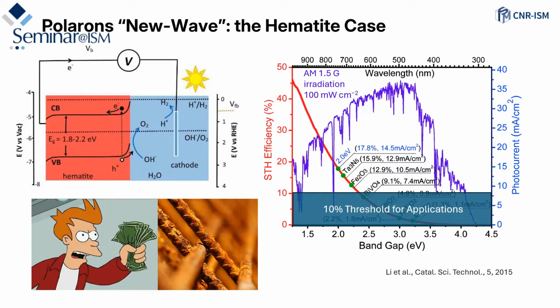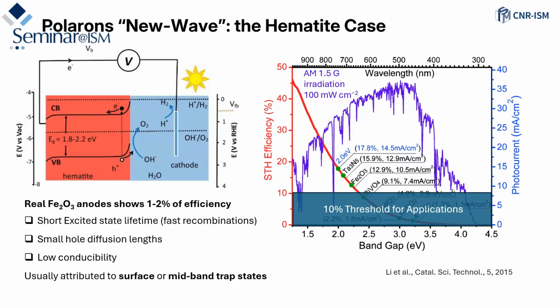And you have to consider that this material is very easy to access, could be easy to implement, and of course is scalable. However, in the real world, we have totally different efficiency. Usually in real anodes, we can only reach like 2% of efficiency. And the researchers ascribed that to surface and mid band trap states, which induce short excited lifetime, small hole diffusion, and of course low photoconductivity.